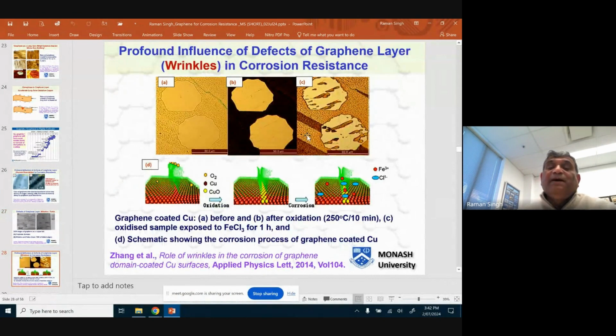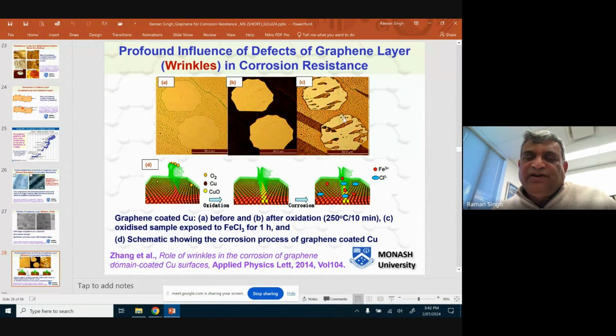And wrinkles are bad for corrosion resistance because people have shown that wherever you have wrinkle, the corrosion can take place there because at the top of the wrinkle, the stresses can be so high that there will be rupture, and corrosive can be passing through those wrinkles, and it will expedite corrosion at those locations. So you can see wrinkles are not good.